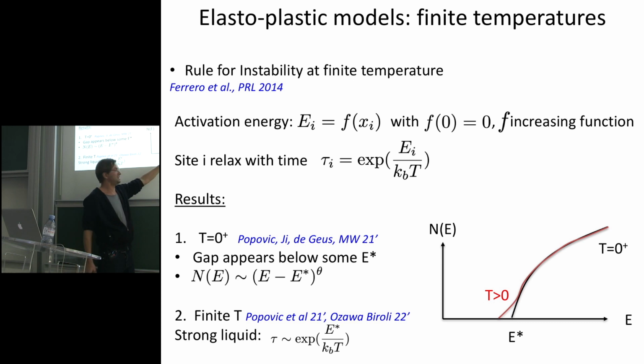The intuition is that if you're at very low temperature, sites that have a smaller energy will relax much faster than sites that have a larger energy, right? Because it's an exponential dependence. So at very low temperature, essentially the dynamics is that of taking the weakest site and relaxing it. Imagine that you have a population of sites, you take the weakest, you reintroduce it there, and you give kicks to the others.